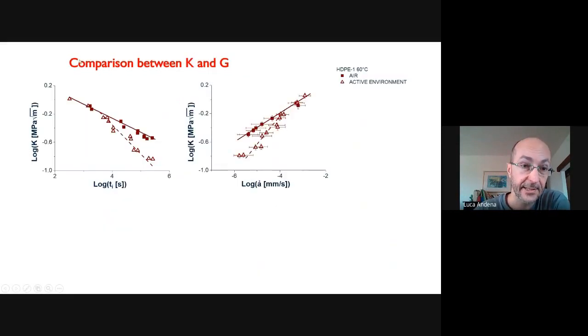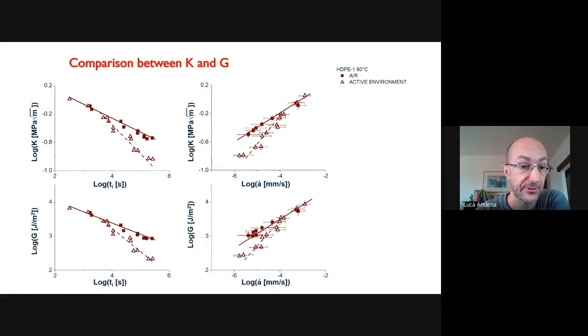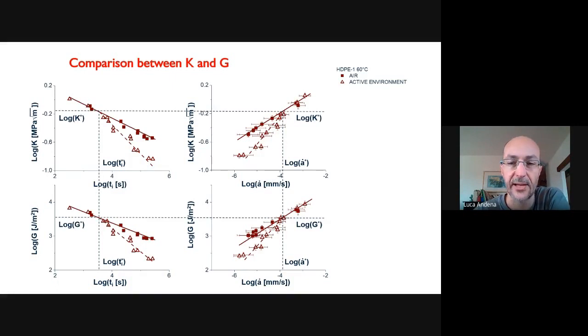Well, if you look at the data, the situation is similar to what we've seen before, with this relationship between the applied load and initiation time, the effect of the environment. Ideally, instead of using K as a representative parameter for describing the fracture process, you could use G, which is an alternative approach. For example, Bamber and his co-workers at Imperial did that, and it works nicely. In linear elastic fracture mechanics, the two are completely equivalent. And indeed, the trends are the same. You get the same characteristic times, and you get these values for the critical interaction parameters.